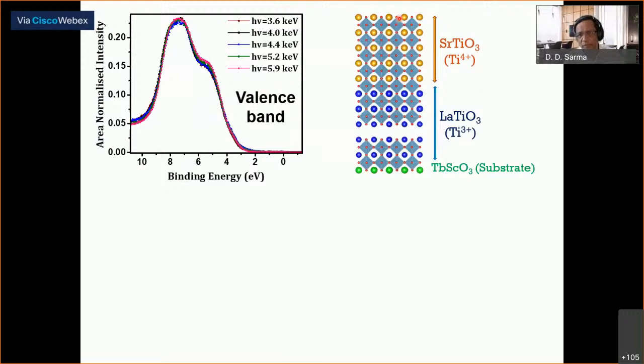This is the sample, strontium titanate on top, lanthanum titanate, and terbium scandate. And there's a valence band. You can see lovely photoelectron spectroscopic data with different photon energies, 3.6, 4.0, 4.4, 5.2, 5.9. And there should not be any problem except for the fact that all spectroscopists know that if there's a very good signal to noise ratio in the spectra, then that is not the part you are interested in.